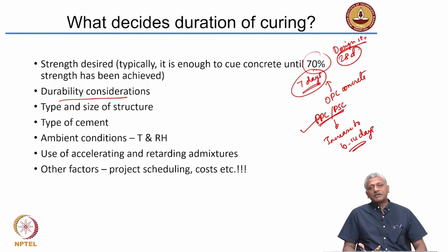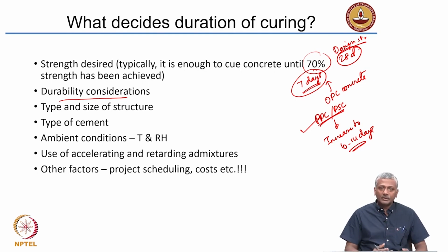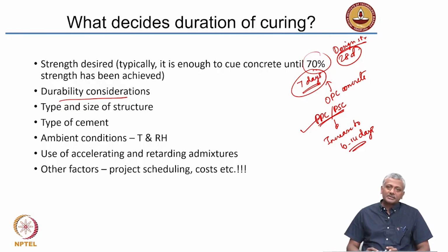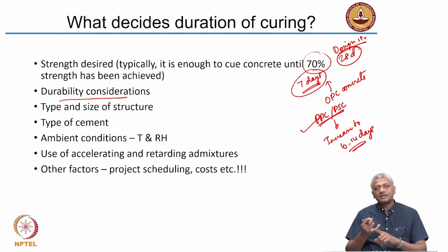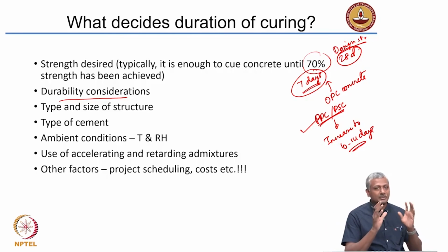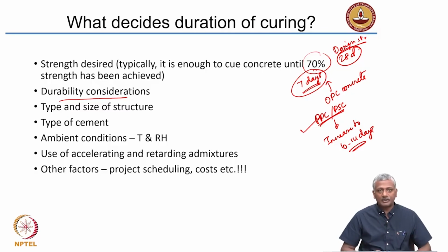If you are using an accelerating admixture, which speeds up the strength gain of the concrete, you do not have to cure for a longer time. If you are using a retarding admixture, which slows down the process of setting and strength gain, obviously you need to cure for longer. Okay. Very often what happens is availability of water ends up determining the length of curing. In some cases, the project scheduling, the amount of money involved to actually do the curing operations, and the workmen necessary for curing. All these aspects need to be considered also, apart from the technical aspects that I have laid out in the beginning parts of this slide.